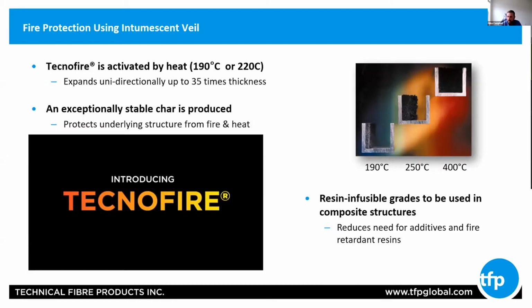Tecnofire is an intumescent veil and is made by integrating graphite particles with high-temperature fibers. These graphite particles expand in a high heat situation, and the process is irreversible. In the top right picture, you'll see an illustration of that. At 190 C, Tecnofire starts to activate, and by about 400 C, it is fully expanded.